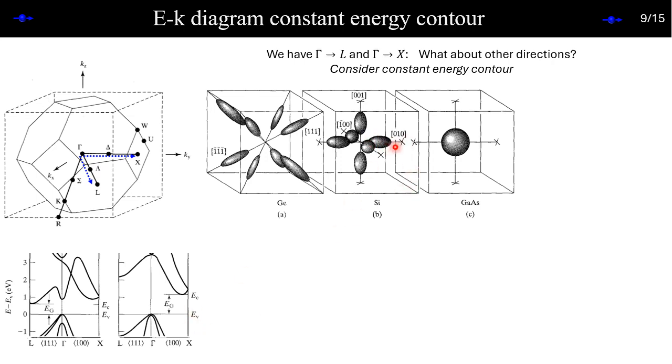So whatever you will see here, you will also have the same copies because of this. You have one, again another here, another here. How many of them do you have? 1, 2, 3, 4, 5, 6, right? So you will have 6 constant energy contours. And they will look elliptical because x and y and z don't need to be the same. The details are hidden in the proper calculation, but if they are not the same, then it will be elliptical.